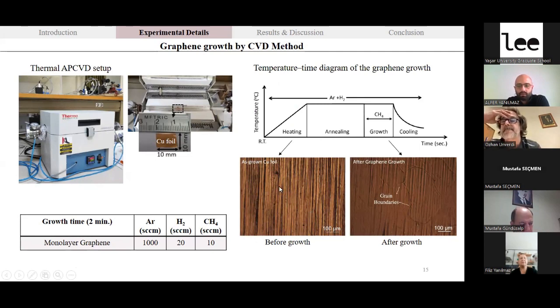Before growth, you can see the optical microscope image of the copper foil. There are such traces here. After growth, with the help of the annealing, the grain boundaries are enlarged. So large-area graphene with low defects can be grown easily. Here you can see the monolayer graphene parameters. With these parameters, it's also possible to grow less defective graphene.